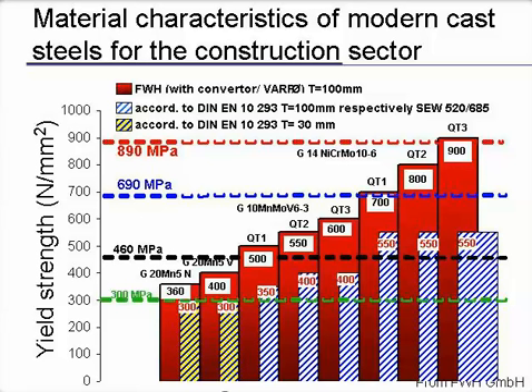And when we look now at the material characteristics of modern cast steel, that's what we see. Here you have the yield strength of the material. Here you have the minimum requirement according to DIN, so the German or also European code, for different thicknesses. And here you have the values that Friedrich Wilhelm Hütte can give you. Depending on the type, here you have 20Mn5, and then you can go higher and higher depending on the quenching and tempering process, up to easily 900 megapascal, 130 ksi, or even higher, but these are not shown here.